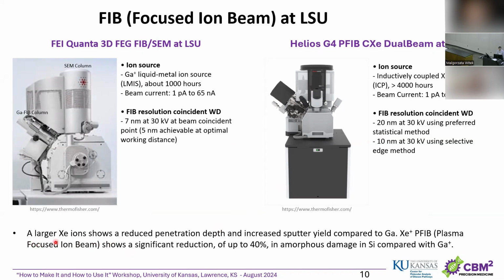Okay. So because the xenon ion is large compared to the gallium ion, what does it mean? When you irradiate those ions on the surface, gallium ions, because they're small, can penetrate into your substrate more easily compared to the xenon. In other words, because xenon cannot really penetrate, all it can do is remove the substrate material. So that's why for xenon-based FIB, the etching rate is higher. You cannot really produce smaller structures, but you can produce the larger structures very fast.